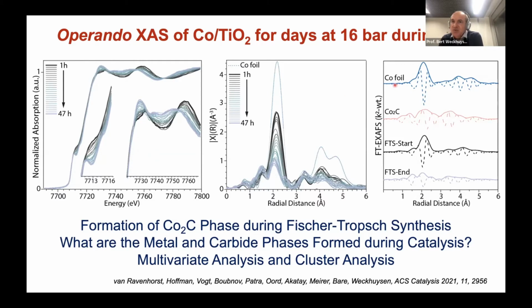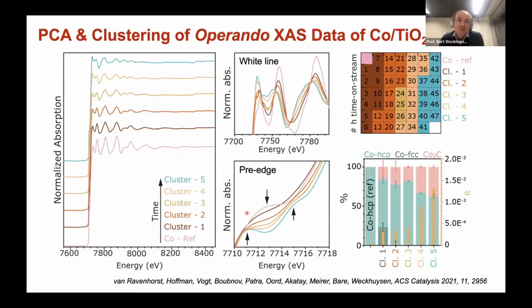I already put here two references, cobalt foil and cobalt carbide. And here I show you the start and the end in the radial distribution function for the XAS. And you can really see that the start is much more like this. In the cobalt carbide, at least you see some contributions, but that I will have now to prove to you. So what are the metal and metal carbide phases present during catalysis? And I will show you first the multivariate analysis and cluster analysis. So we did this. We did a principal component analysis on all the data.